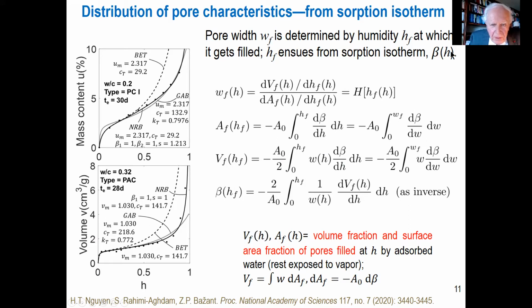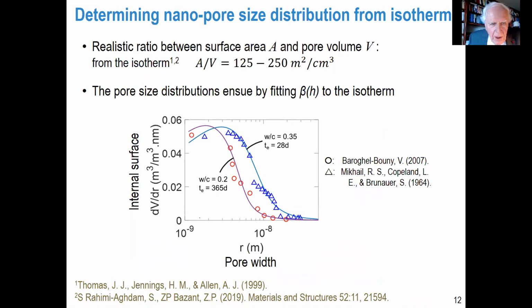So that's beta F. So volume filled is expressed this way, and now we have here the volume of water per unit volume of concrete or cement paste, and the surface area of the adsorbed layers, also per unit volume of concrete. They are calculated from this parameter beta, the derivative times the already water-filled layer, and so forth, and finally the beta function. So this is all easily obtained and easily computed and can be constructed.